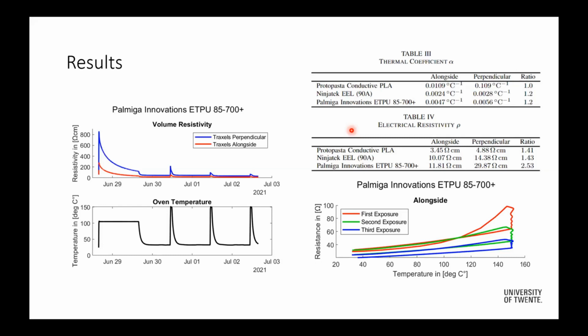And the interesting thing is the top one, the PLA material, which is kind of a stiff polymer. You can see that the temperature dependence is not really that affected by the anisotropy, but the TPU, which is flexible and has all these elastic effects in there, you can see that the anisotropy is there. And even if you vary printing settings to be even worse, which you did in a different experiment, it gets quite worse. You can really get these big voids, and then you really see the thermal expansion because your network is touching point and really varies a lot.